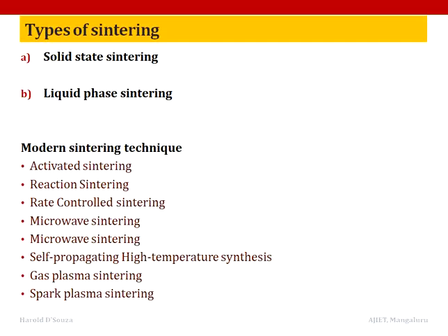Modern sintering techniques. Activated sintering. Here the addition of a small amount of an alloy element, called doping, in certain metals and alloy systems increases the rate of densification by as much as 100 times compared to the undoped compacts. This is known as activated sintering. Now, the best known example of activated sintering is the doping of nickel in tungsten compacts. Nickel, which is added as a solution of its salts, gets reduced during sintering and forms a coating of a few monolayers on the surface of the tungsten particles.